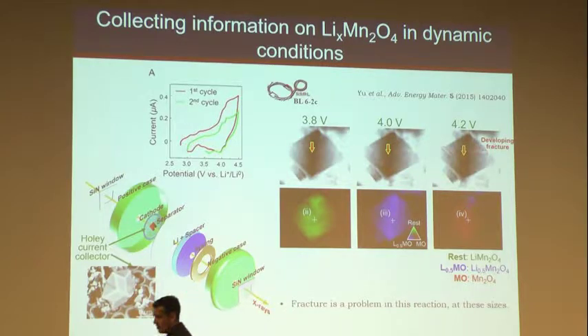And so this is a different material. This is a manganese oxide, again a spinel, but it's not a spinel with nickel, it's just manganese. We're still removing lithium all the way to lithium 0. So we have manganese 3 going to manganese 4. This is an experiment done at the manganese K edge. So we collect 2-dimensional images, and then we scan the potential. That's the electrochemistry plot that you get.